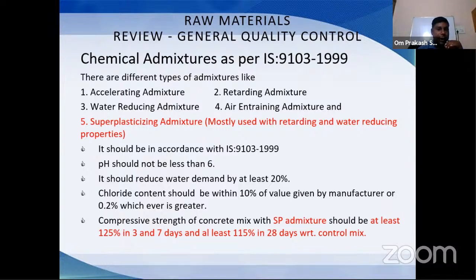So what should be the properties of admixture? Certain properties are given in Indian Standard 9103, which we will not discuss here. The most important property is pH, just like water. The admixture should not have a pH less than 6. And if we are using a chemical admixture in concrete mix design, it should give around 20, 25 or 30% water reduction. If we are taking it just for 5% or 7% water reduction, then it is of no use. It should not have any chloride content, or if it has, it should be well within limits. And when we are using the superplasticizing admixture, the strength of concrete should increase with respect to the control mix, which is prepared without the admixture.